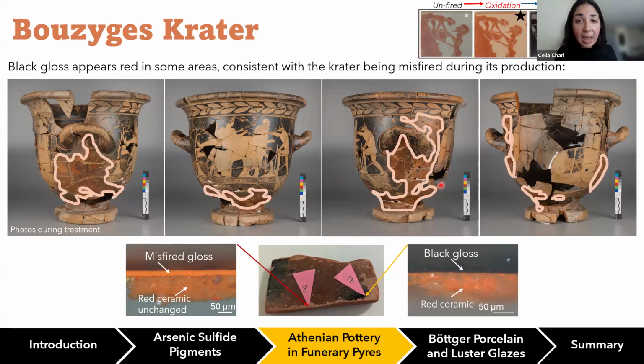And this could have either happened in the first oxidation step, if the glass trapped the iron oxides and solidified too quickly, and maybe the other reduction and oxidation steps were carried out at temperatures that were lower than they should have been. Or it could alternatively have been carried out in the last oxidation step if the gloss layer was not completely impermeable to oxygen diffusion, and we might have seen some resulting patches of red gloss emerge because of differences and, I guess, errors that occur during firing.